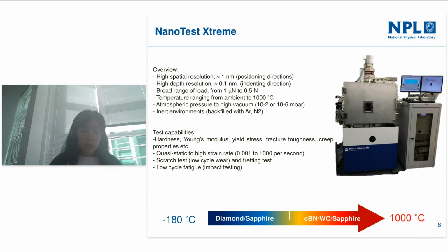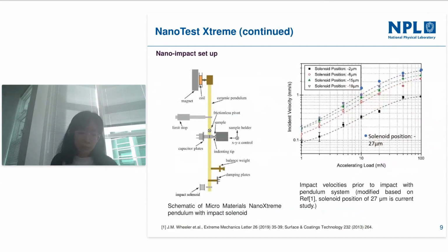So the first test technique I'm going to introduce is the nano impact. The figure on the left is a schematic setup of the pendulum with impact solenoid, which attracts the lower part of the pendulum towards the magnet before the test, and releases to start the test. And the coil on the top provides an acceleration force to enable the indenter to land on the surface of the sample at high speed. And the high frequency data sampling enables us to record the depth profile as a function of time.